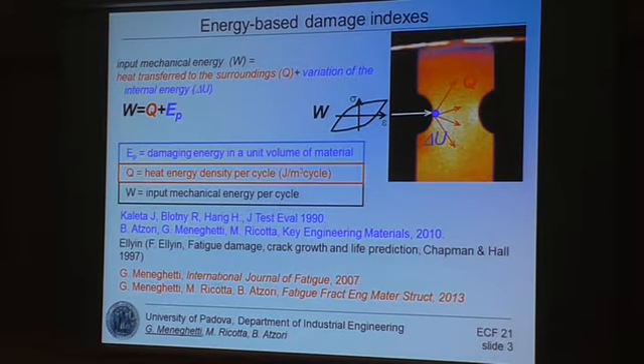Of course, up to a given strain rate. We all know that if you increase very much the strain rate, this energy partition may change. So it is a material law depending on the strain rate. But in standard fatigue tests, 10 Hz, 20 Hz, this energy partition is a material law. And to complete the answer, we did some dedicated tests where we artificially varied the thermal boundary conditions, for example, blowing fresh air or hot air into the specimen, and also varying the test frequency, because if the test frequency increases, of course the temperature increases, and you always measure the same thermal energy release, more specifically heat loss.